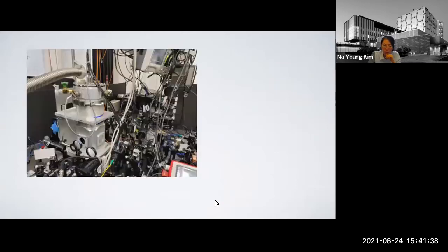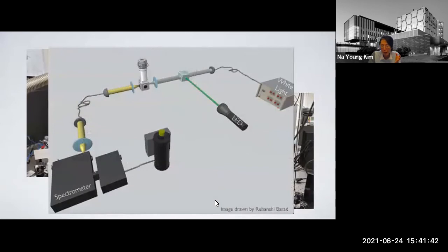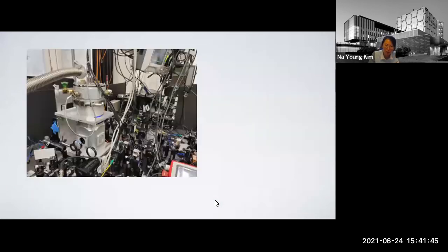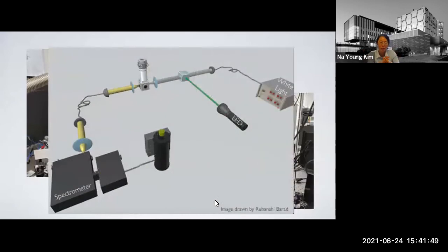So let's go into the lab. These are our lab setups. It looks a little bit complicated, but in fact this is the simpler version of the setup. Basically, you need 3 things: a light source, a sample, and a detector. We placed the red shiny sample, which I polished in Tokyo, in a specially designed holder, because cuprous oxide doesn't like strain. I learned from my colleagues the strain-free holder to place it into the cryostat, and we performed the absorption spectroscopy in the transmission configuration by varying the temperature from 4 to 100 Kelvin. So that's what we have.